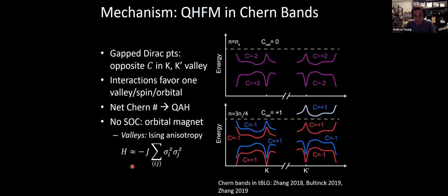And very interestingly, in these systems, there's likely very little role of the spin at all. There's almost no spin-orbit coupling in carbon. So you have something that looks like an Ising ferromagnet in some regards, but is probably not based on the electron's spin at all. It should be essentially a purely orbital magnet, where this is really valley polarization.